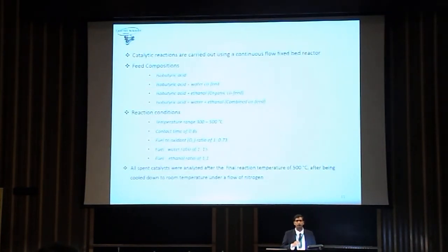So after we investigated what's happening under reduction and oxidative environments, it gave us more insight to investigate what's happening under the real oxidative dehydrogenation environments. As we observed from the reduction and oxidation experiments, it is happening in two steps, and the temperature of the reoxidation is also affecting the formation of these phases.